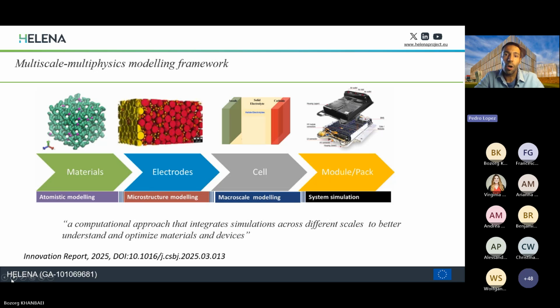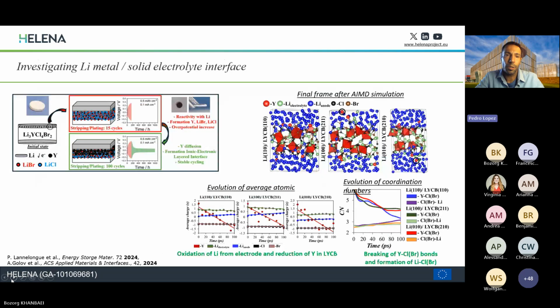So here the goal is not only to improve materials and battery performance, but it's also to be able to predict the battery performance in the long term cycling. And here is some example that you will see in the next slide, in which thanks to ab initio molecular dynamic simulations, we were able to elucidate some important aspect of this technology, which is the reactivity between the lithium metal and the solid electrolyte interface, which is key to ensure high performance devices.